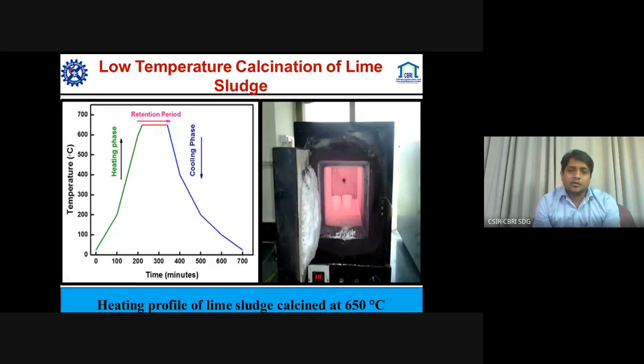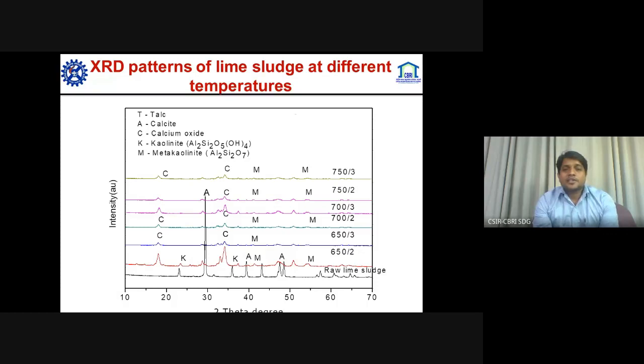And the heating profile was 650 degrees C, kept for 2 hours. When we look at the raw lime sludge, kaolinite was present in it, but with the heating treatment at 650 degrees C for 2 hours, it was converted to metakaolinite. The other XRD spectra are for higher temperatures, but they produced the same result. So we optimized it at 650 degrees C.